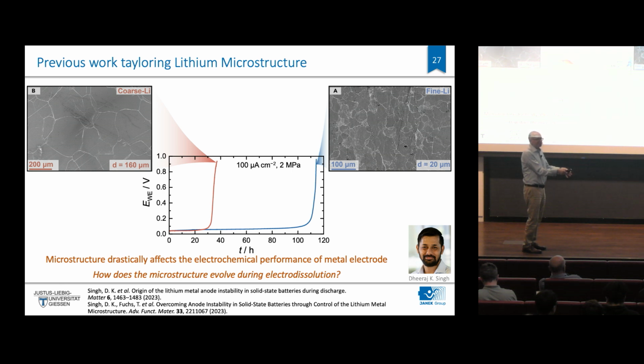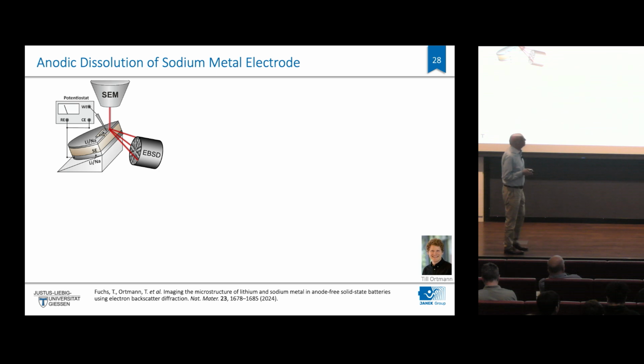And then, of course, the question is, what is the microstructure of the metal that's being formed in the cell? Well, then the microstructure of the foil is irrelevant. It's more the question, what is really the microstructure of your film? And that's where Till and Till, we call them the Tillies in the group, did their work. So they were making a little solid-state battery. They made a cross-section with a FIB, all under cryo conditions. And then they were able, even operando, to look at the lithium metal electrode in principle and investigate the microstructure during operation.